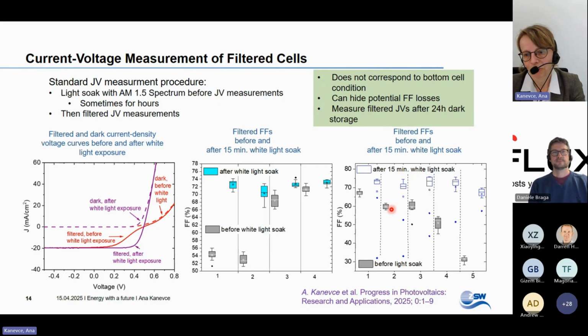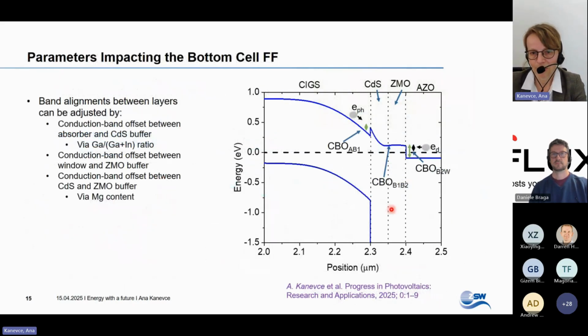Okay, what is causing my fill factor loss? What is causing the S-shaped curve? How can I design myself in order not to have it? Well, the usual suspects are band alignments. This is a part of the equilibrium band diagram of a CIGS solar cell. There are secondary barriers all over the place. The barriers in this direction would inhibit the motion of the photoelectrons and therefore create fill factor loss. The barriers in this direction would create a barrier for electrons in the diode direction and create lower turn-on voltage.